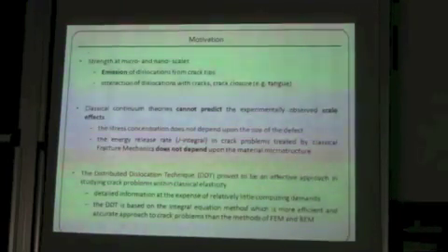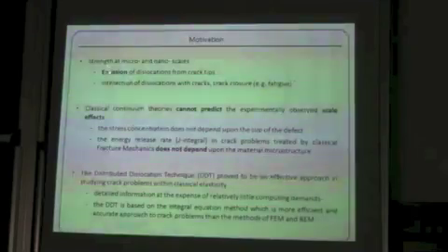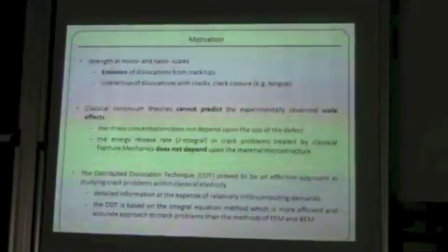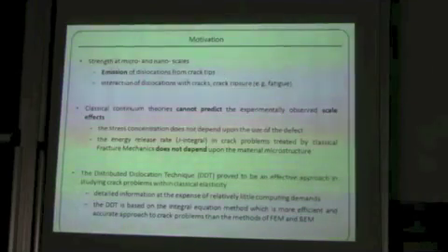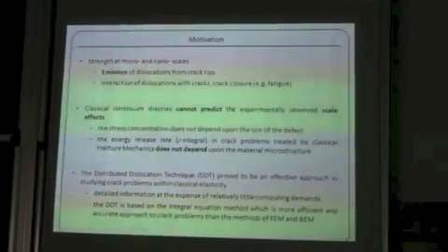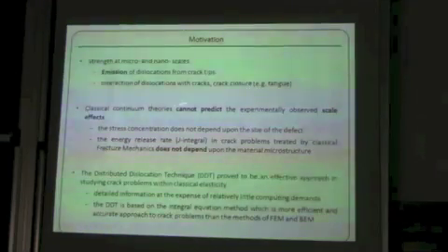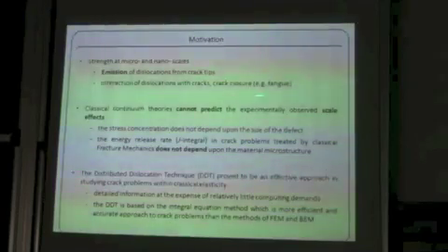The motivation for this study is to investigate strength at micro and nano scales. Indeed, cracks are known to emit dislocations in order to lower the local stress intensity factors and are shielded by this phenomenon. Further, this interaction may, in some cases, lead to crack closure, which is an important issue in fatigue.